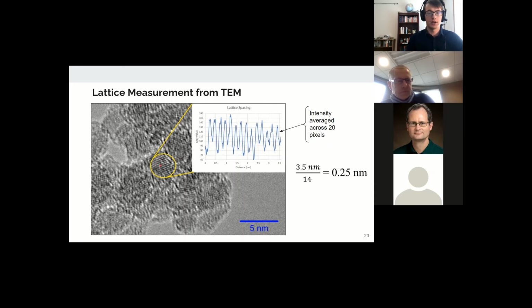A brief calculation of the example in this figure shows that the average lattice spacing for the nanocrystal is equal to the size of the nanocrystal, or the diameter, which was 3.5 nanometers, divided by 14, which is the number of lattice planes that can be counted just by counting the peaks of those lines. That comes out to 14. So 3.5 divided by 14 gives us 0.25 nanometers, which is the expected dominant 111 lattice spacing for beta silicon carbide. And that's one piece of the evidence that leads us to believe that this is, again, the cubic form of silicon carbide.